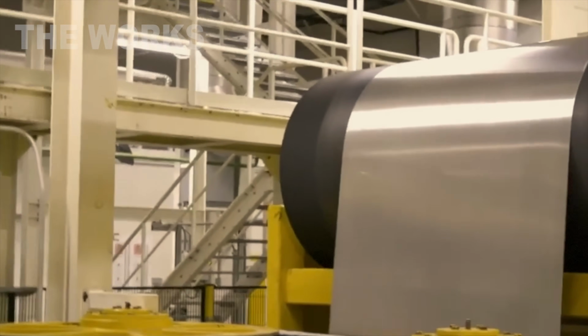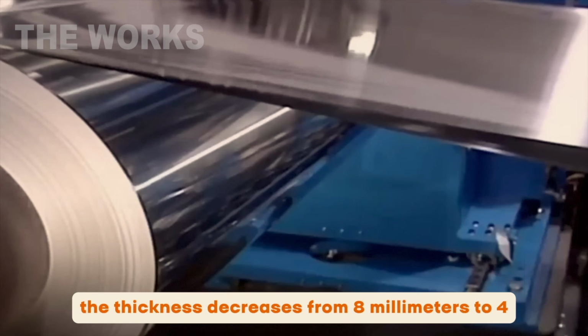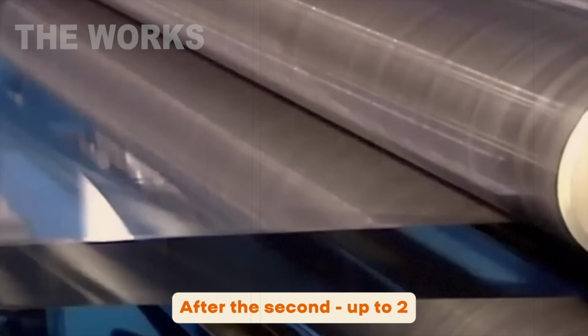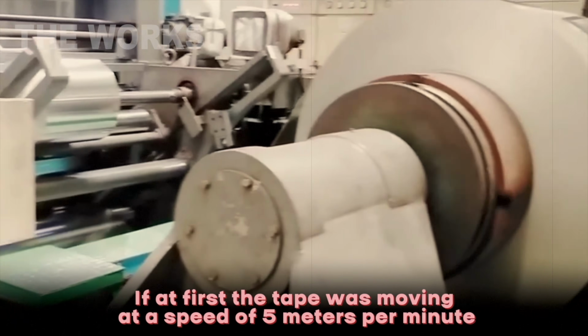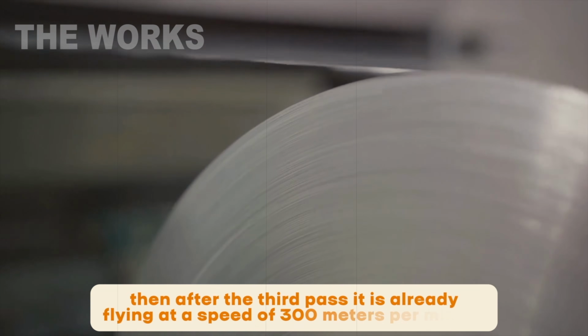After the first pass, thickness drops from 8 millimeters to 4. After the second, down to 2. Speed builds. If at first the strip crawled at 5 meters per minute, after the third pass it's flying at 300 meters per minute. Air whistles.